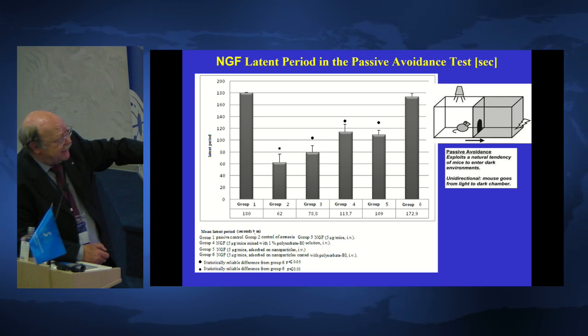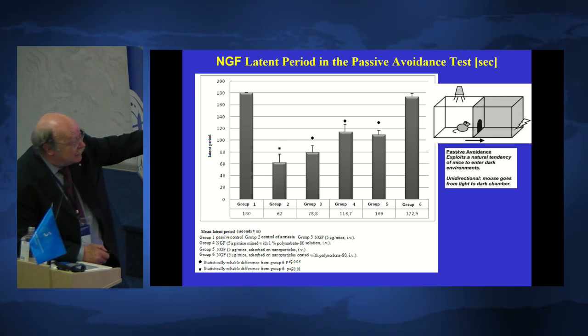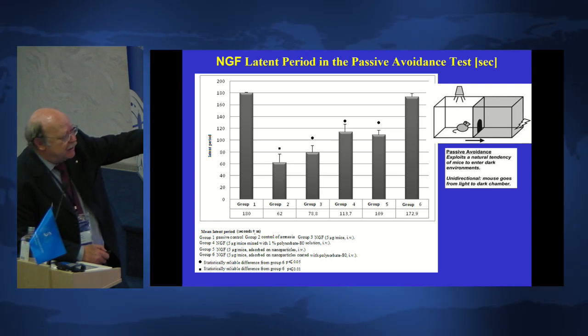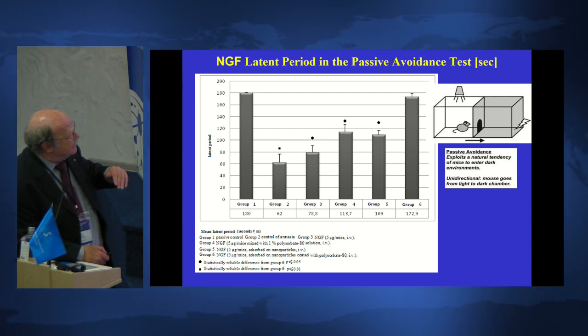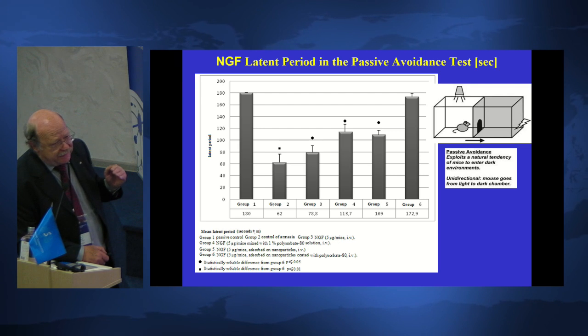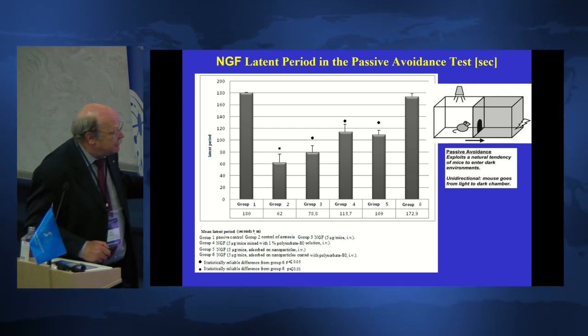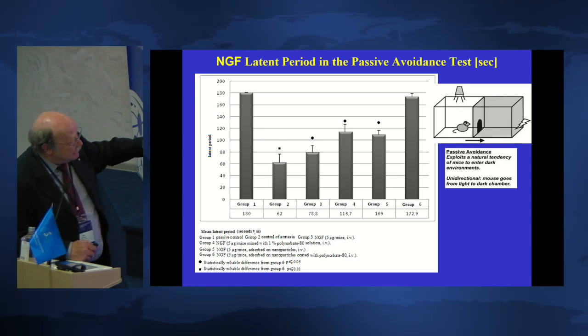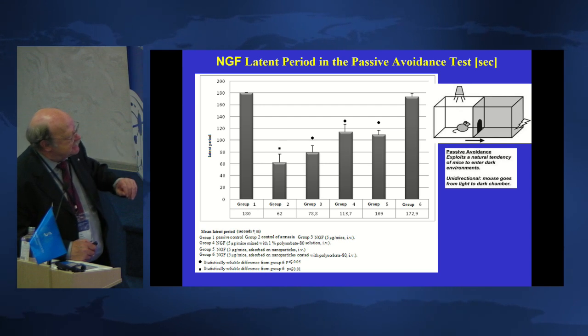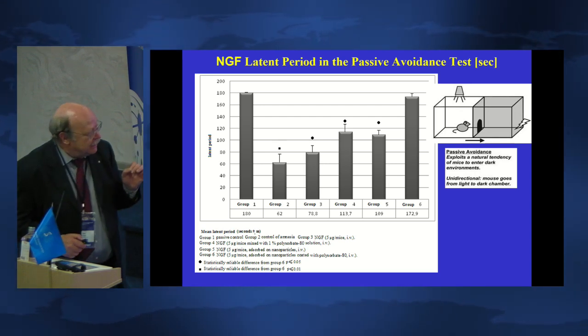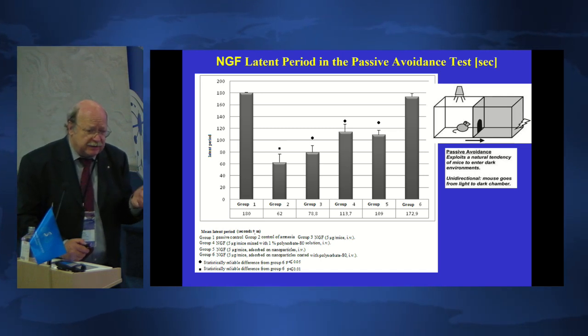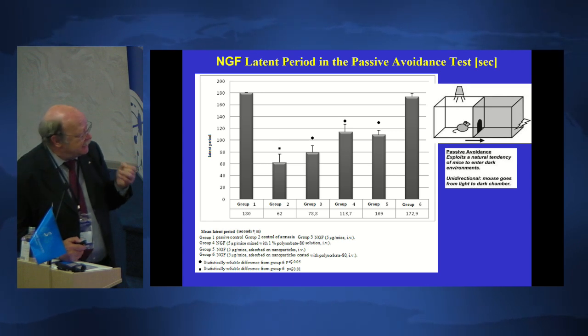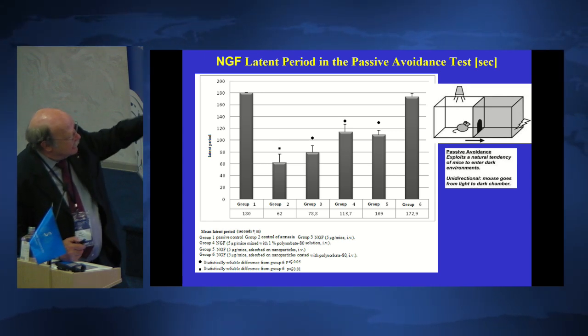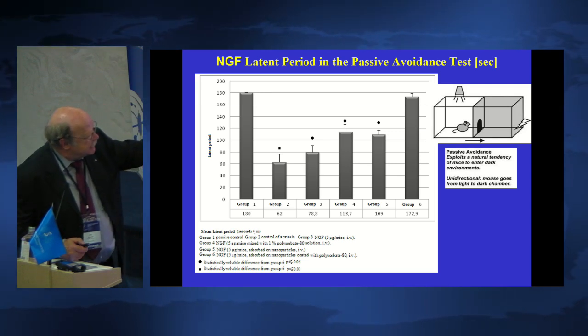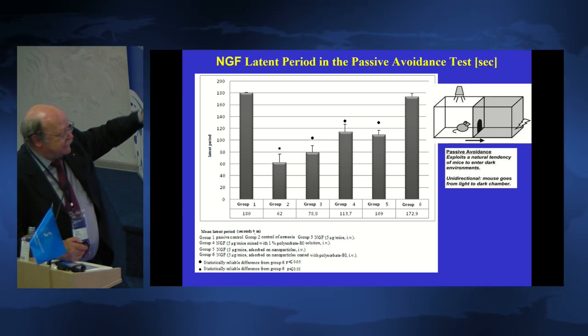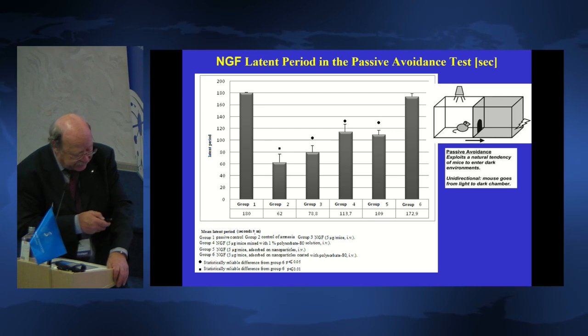They like to go into the dark side, but then they are trained for a week. They know that they can get an electric shock there. And so the latent period, you see it in group one, is about 3 minutes when they know that they can get a shock. When you then inject scopolamine, they forget. That's group two. And then we go to group six, because the others are just controls, and you can see that with NGF bound to the nanoparticles and then overcoated with polysorbate 80, they remember the old effect, and you get a non-significant difference to what they did before.